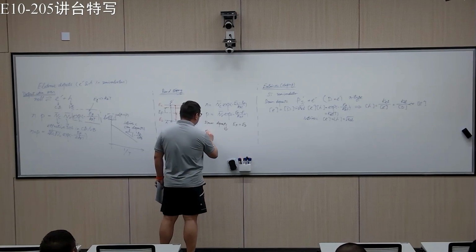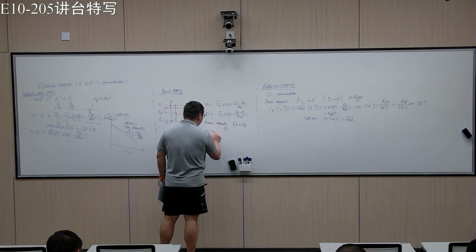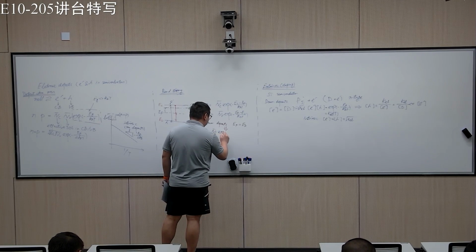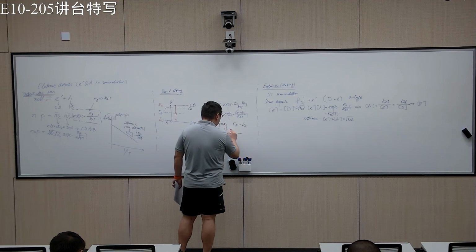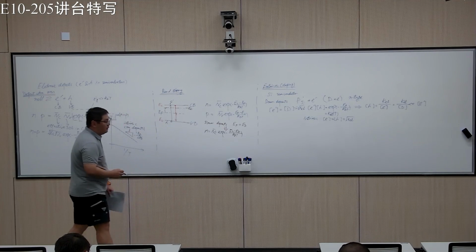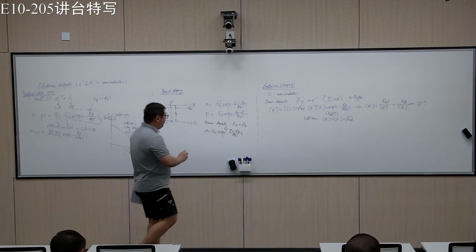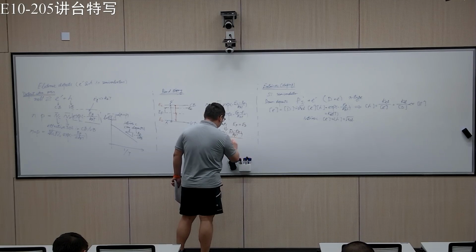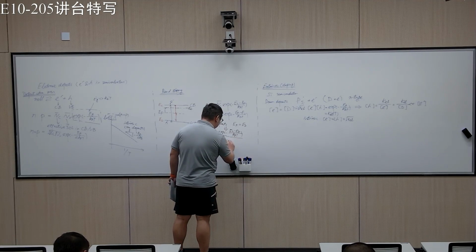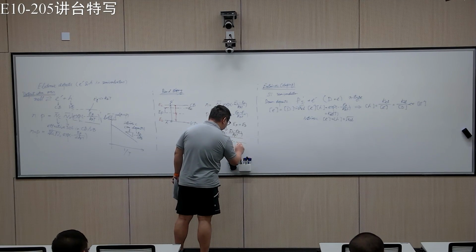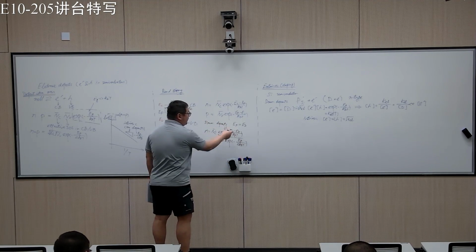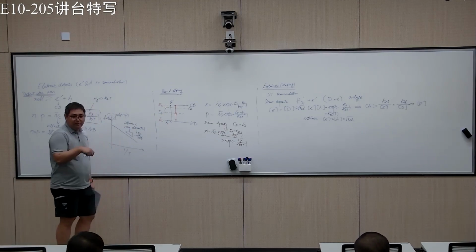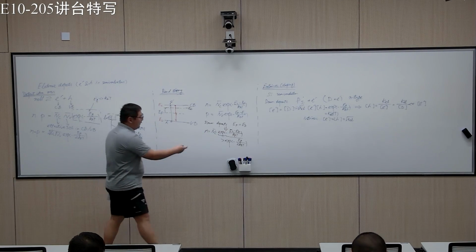For the electrons, now we have NC exponential of minus (EC minus ED) over kBT. You can see here, this is now much larger than exponential of minus Eg over 2kBT, simply because this is much closer. It's a much smaller value, with a negative sign here.